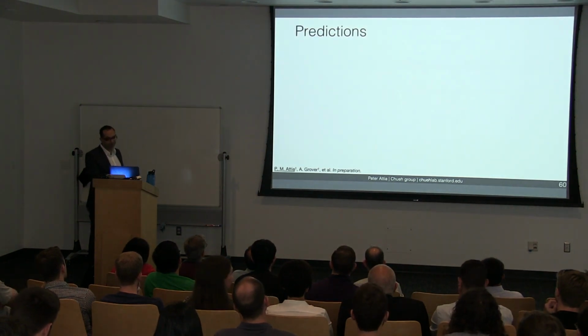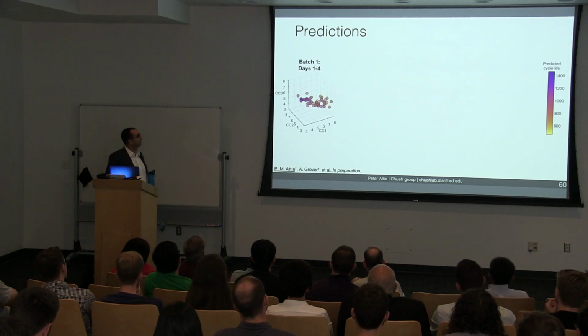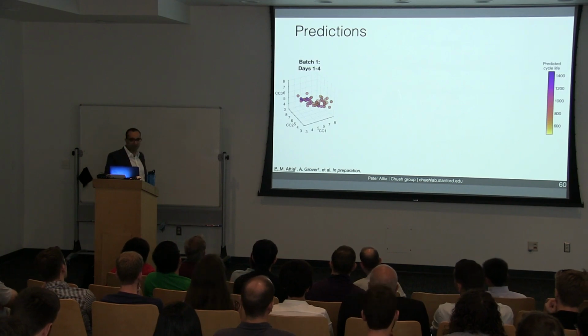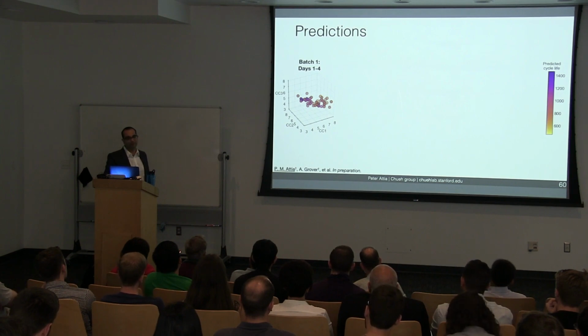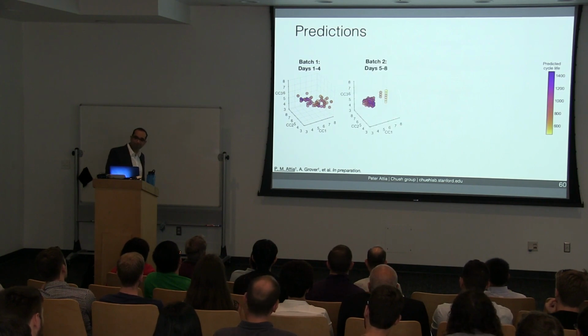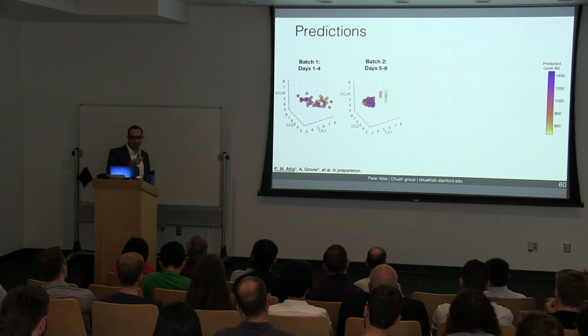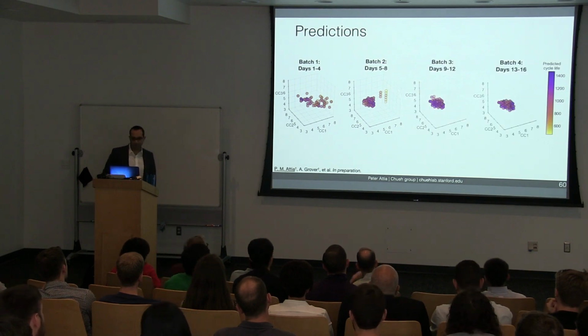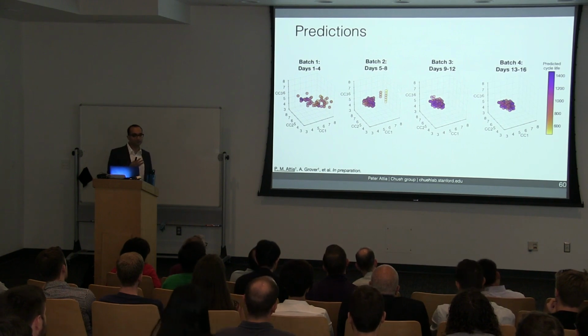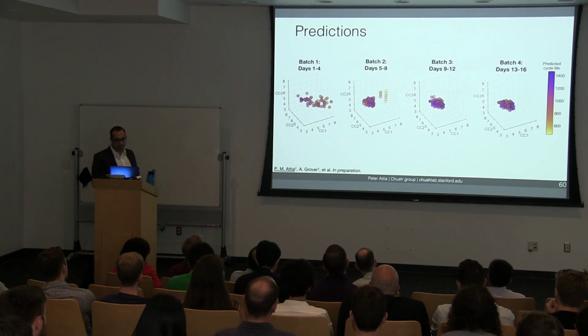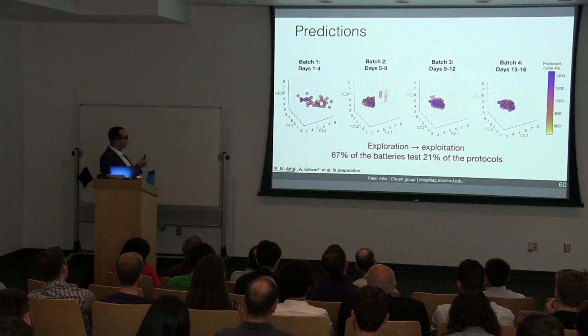So here's a closed loop in action. We start by testing a random subset of the protocols. Again, instead of cycling to failure, we're using the predicted cycle life using the first 100 cycles. So each batch only takes around 4 days. In batch 2, we've started focusing on the most promising region of the parameter space, but we're still doing a bit of exploration. By batches 3 and 4, we're only collecting data from the most promising protocols. So we can clearly see the transition from exploration in batch 1 to exploitation in batch 4.